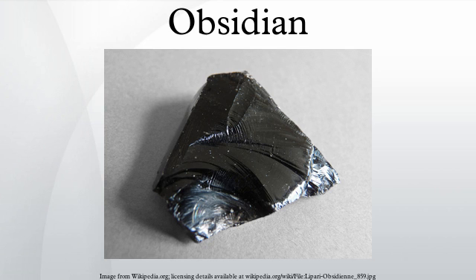Current use: Though not approved by the U.S. Food and Drug Administration for use on humans, obsidian is used by some surgeons for scalpel blades, as well-crafted obsidian blades have a cutting edge many times sharper than high-quality steel surgical scalpels — the cutting edge of the blade being only about 3 nanometers thick. Even the sharpest metal knife has a jagged, irregular blade when viewed under a strong enough microscope, whereas when examined under an electron microscope an obsidian blade is still smooth and even. One study found that obsidian incisions produced fewer inflammatory cells and less granulation tissue at 7 days in a group of rats. Don Crabtree produced obsidian blades for surgery and other purposes, and has written articles on the subject. Obsidian scalpels may currently be purchased for surgical use on research animals.